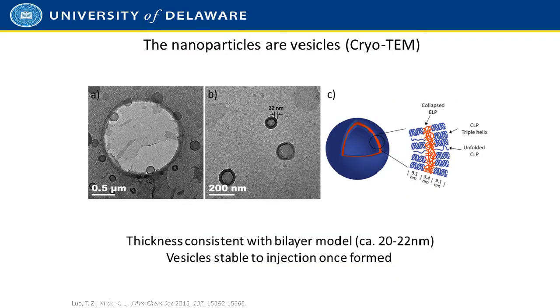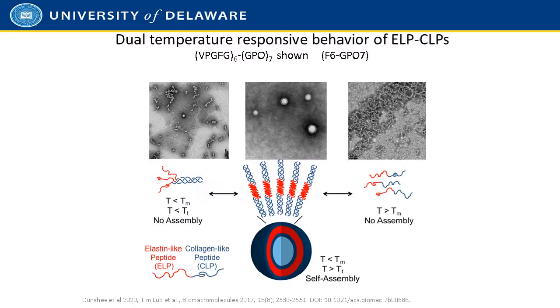We know that the particles have the vesicle structure that we thought they might because of Cryo-TEM results that clearly show the sort of bilayer structure on the exterior, on the surface of these spherical nanoparticles. The thickness of that layer can be measured easily in the image analysis, and it's on the order of 20 to 22 nanometers, which is perfectly on par with the expected diameter of a bilayer of these collagen-elastin constructs. We make the vesicles. They're stable.